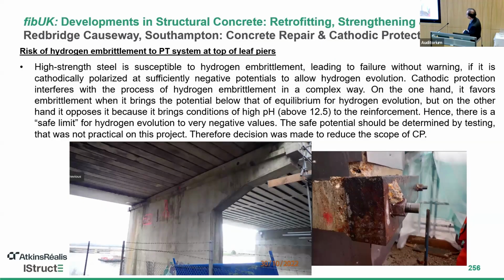One of the challenges that we had at 2 piers of the structure was the interaction between the CP system and the high tensile PT system, which was installed at the top of the piers. As you may know, high tensile strength, high stress steel can be affected by high negative potential. And the high potential can generate hydrogen atoms and molecules within the matrix of the steel, which cause fracture and sudden failure.